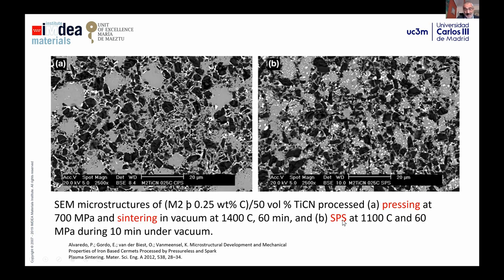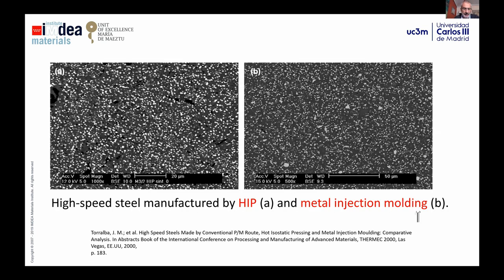By spark plasma sintering, at a much lower temperature and lower pressure, and just 10 minutes, you can reach a much better microstructure with more refined grain, but for the same application with much better properties. And there is another example.